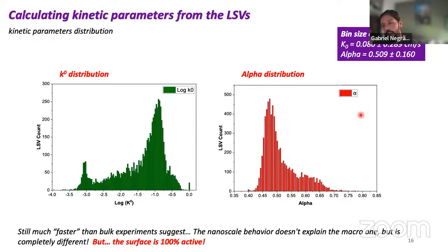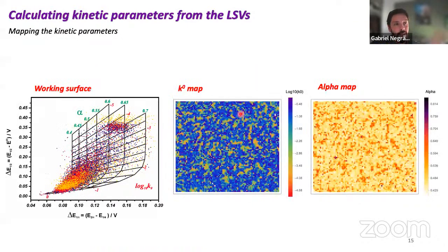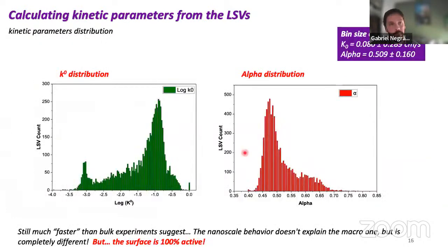An argument could be made that we could even try to go down with some techniques and do the atom level. And of course, there are efforts in that direction, with people trying to do single atom catalysis and stuff like that. But that's again the take-home message: the bulk behavior is quite different. It's not a representation of the actual surfaces, and surfaces can be quite heterogeneous, right? So the CV that we got is a mishmash of all those K0s happening. And if you do the bulk experiment and get a K0 from that, we're going to get a K0 that's actually different from any of the K0s we see in this distribution here.